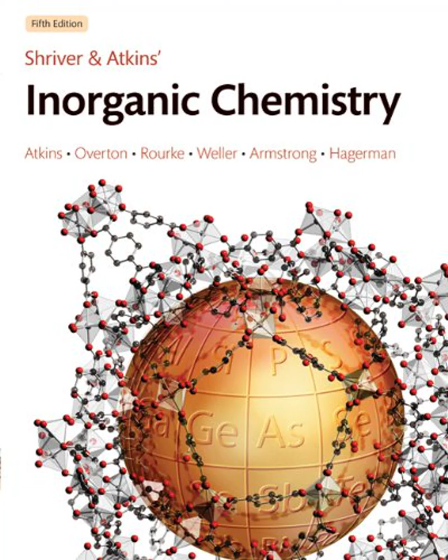Okay, and another wild property linked to perovskites, colossal magnetoresistance. What's that about? It sounds dramatic, and it is. Certain manganese-based perovskites, the manganites, show this massive change in electrical resistance when you apply a magnetic field, especially near their magnetic ordering temperature. Like how massive? We're talking orders of magnitude, sometimes resistance drops by a factor of a billion or more. It can change from an insulator to a metal, just with a magnetic field.